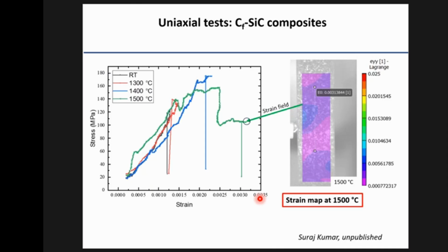shall we say, a reasonably acceptable plus or minus over what the company thinks is a constant temperature zone. We actually find that we can only take a smaller region in order to get reliable data for, let's say, plus or minus 5 degrees. With the extensometer, what the manufacturer gives you is plus or minus 10, which is okay if you go by ASTM standards, but if you want precision, it may not be okay. It depends on how sensitive your deformation is. So this is a fiber reinforced material, and the strains are not very large. You get up to about 0.3% or 0.2% when everything breaks.